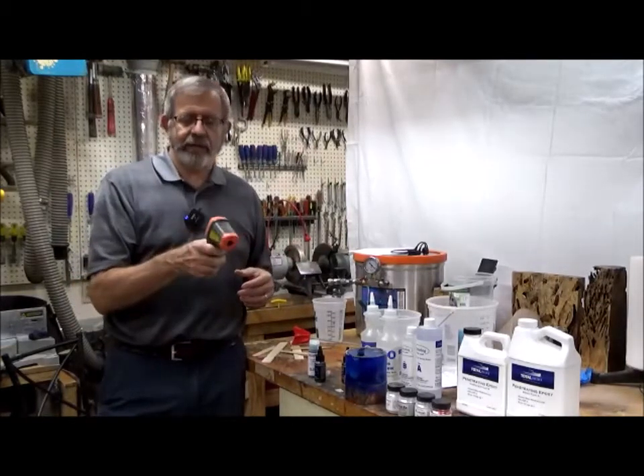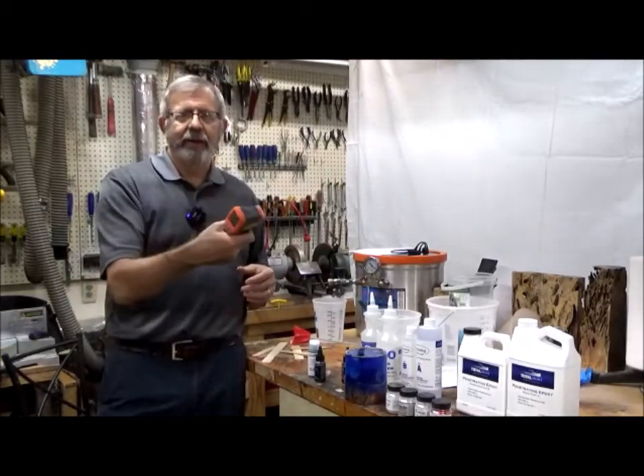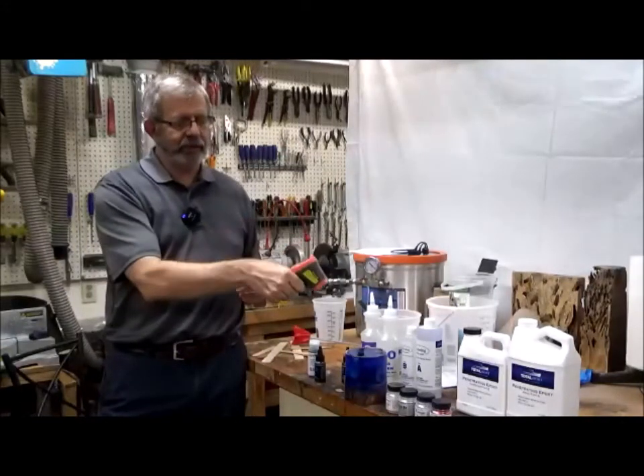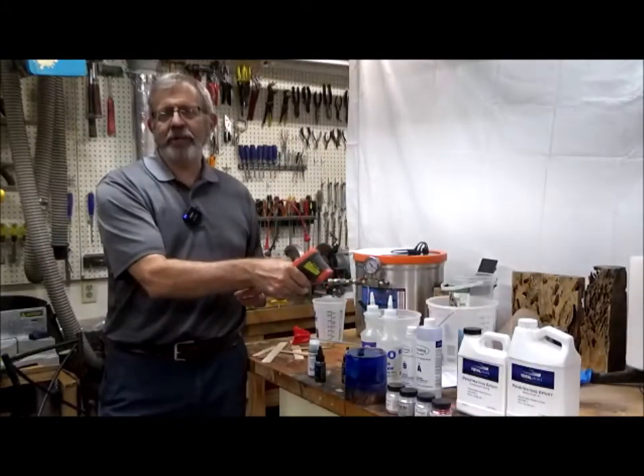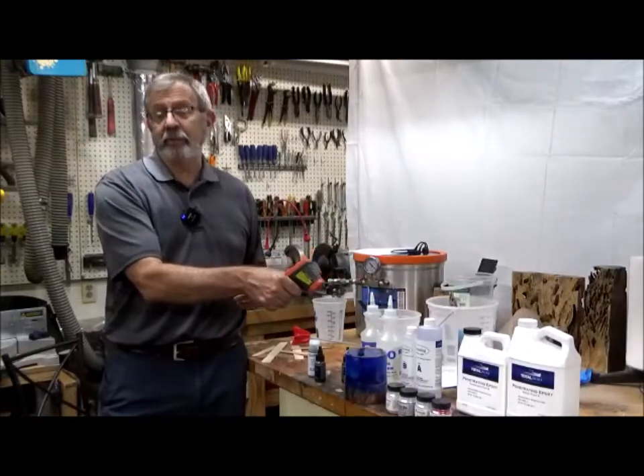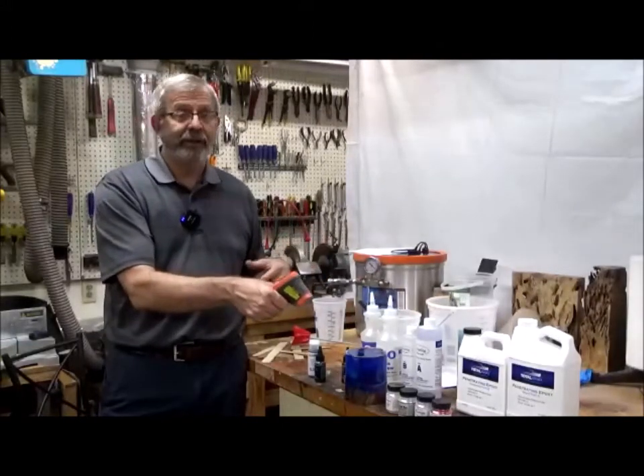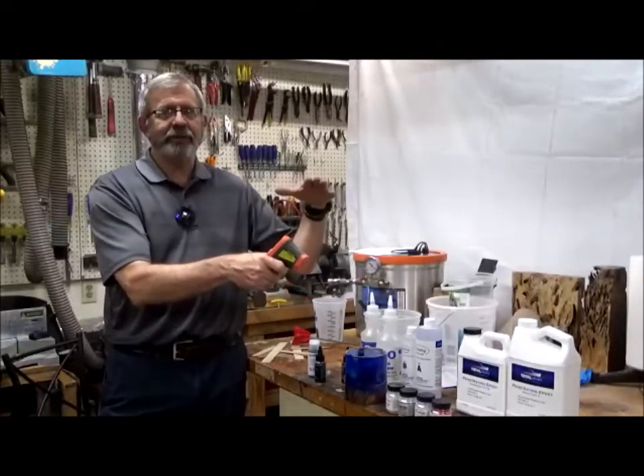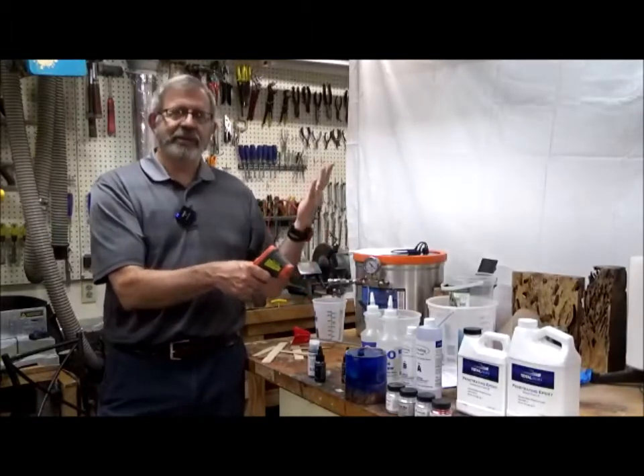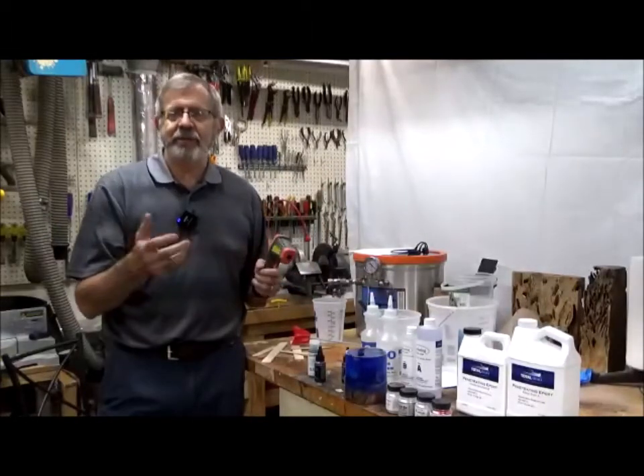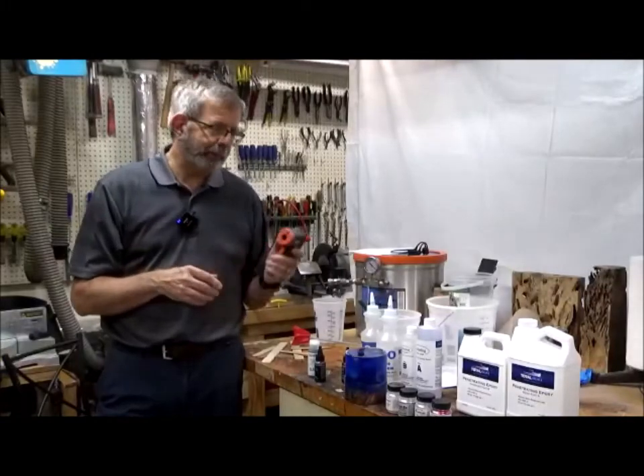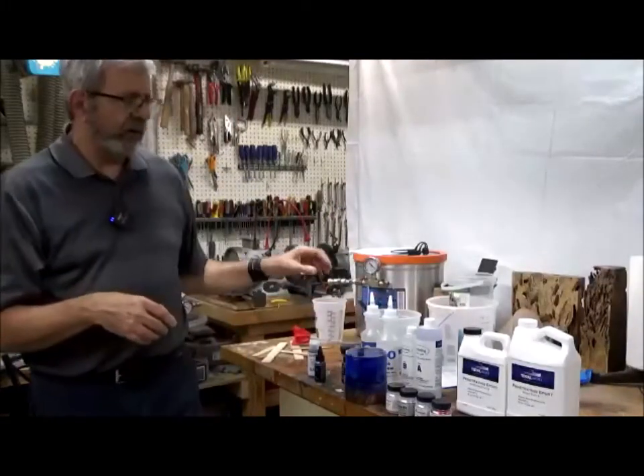The way I do that is this is just an infrared temperature sensor, and you press on it and point it at something, and you can just watch the temperature go up. I start at about 70 degrees, and it gradually climbs. And I just learned from experience that 95 is the magic number to make that work. As far as molds go,